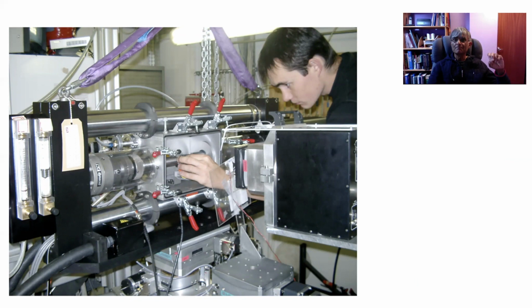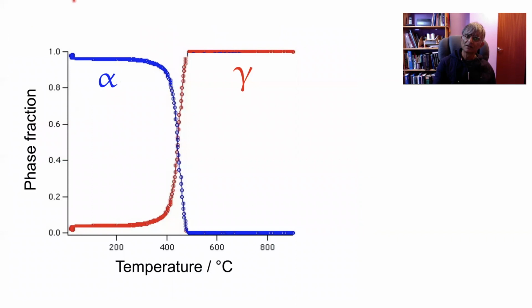Now, if you have a good experiment to do, then you can write a case for using such facilities if you are in universities, completely free of charge, on the basis that you publish the results, which is not an issue. And in addition to the stress strain behavior, you can get a very clear idea of the phase transformations happening as your constrained tensile sample cools. Of course, we are using X-rays, so we can work out phase fractions, lattice parameters, and even the partitioning of carbon if carbon were to be there.